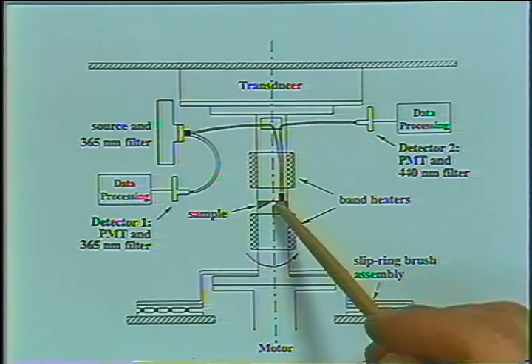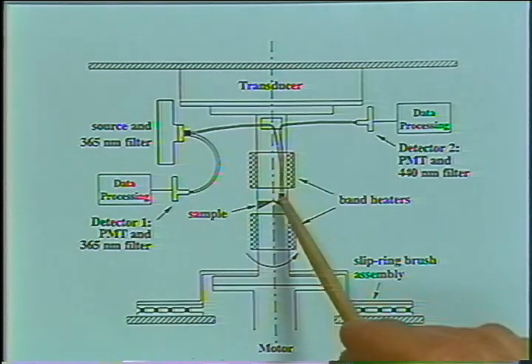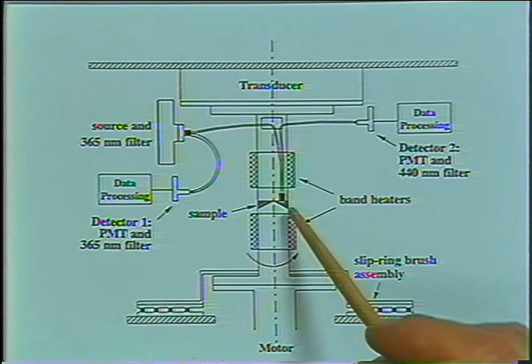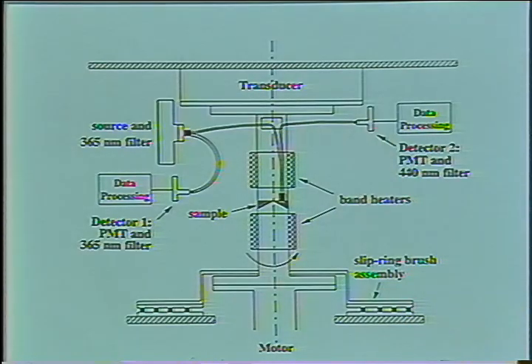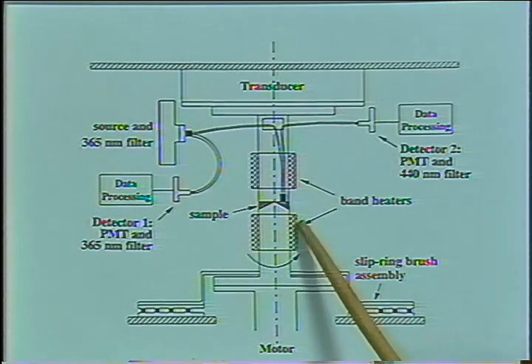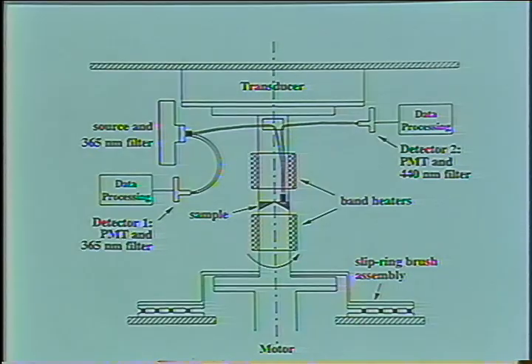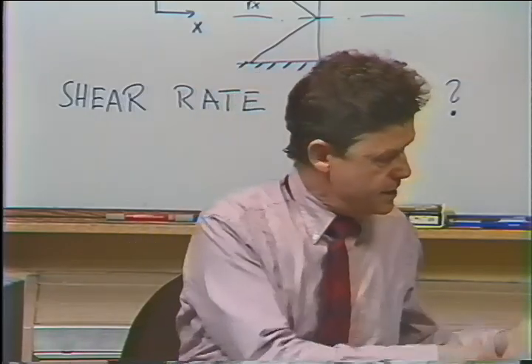There are some more features that we will come back to later when talking about blends. We have an optical probe here. We measure fluorescence of the sample. Basically the incoming light is absorbed in the sample and changed to different wavelengths, and then its intensity and the fluorescent wavelength are measured. And this way we can look at phase transitions. We can perform measurements on the angstrom level. So the cone and plate geometry is very advantageous for optical studies in addition to the rheometry studies. You can combine that very nicely. So that's a nice feature. Let me come back now to the cone and plate rheometer itself.